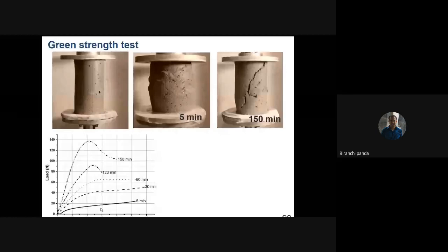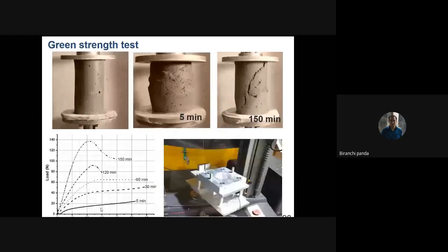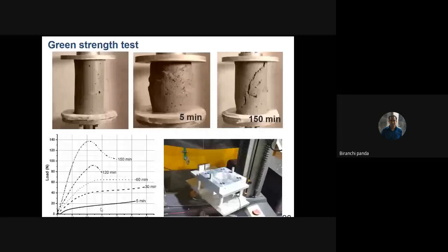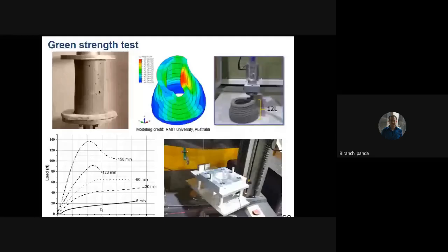Then we did some direct shear tests. The shear test is going to give you the shearing property of the material. With the compressive strength and shearing strength, we tried to develop a model in collaboration with another university in Australia. This model is very helpful because now we have a tool to predict when the material is going to collapse. It's very useful because when you are printing a tall structure, 3 meter, 4 meter, if after completion of 2 or 3 meter the whole structure collapses, it is going to be a nightmare.